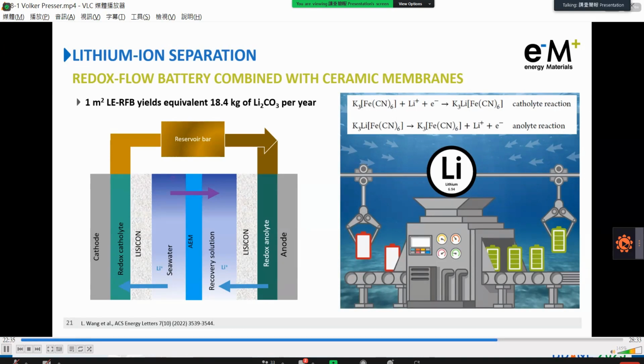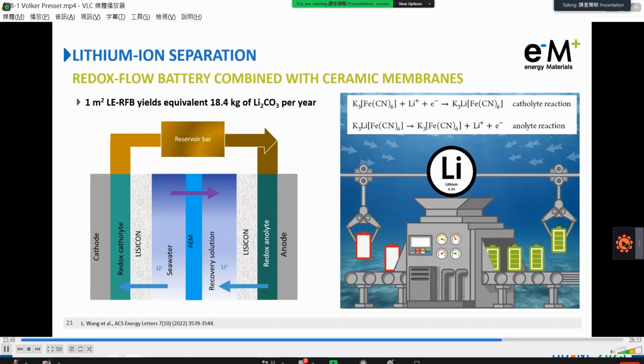Lithium, and in this case only lithium because of the extreme high selectivity of Lisicon towards just lithium, was uptaken into the redox catholyte to balance the charge imbalance triggered by the redox reaction. The redox catholyte was then, over a reservoir, pumped into the anolyte compartment, where the reaction there released the lithium plus through the Lisicon membrane into the recovery solution.